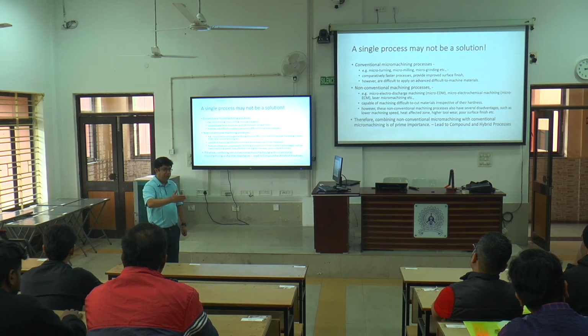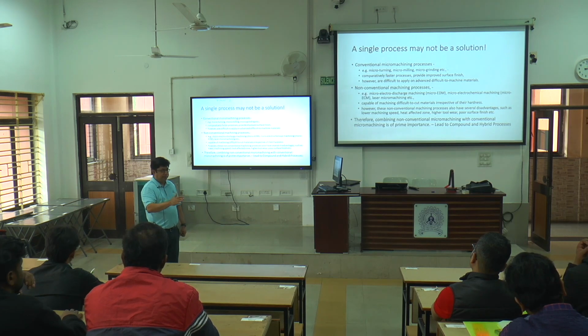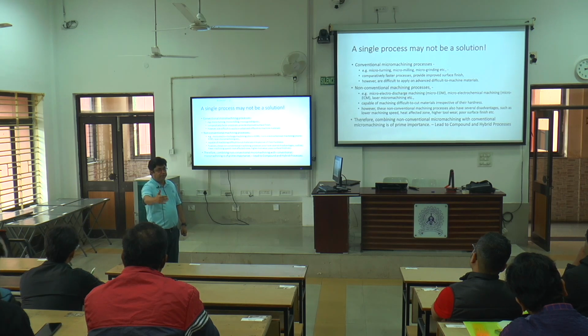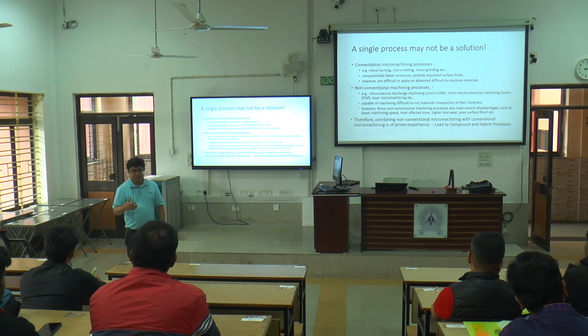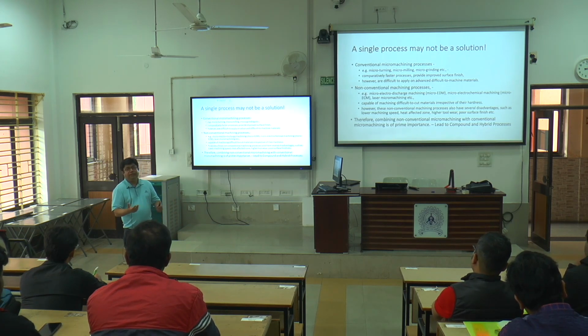So that means if you are machining, on the first layer there is some oxide formation, right? And then you have some recast layer, right? After the recast layer, you have some heat affected zone, and then you have the material. In the recast layer, definitely the properties are far different from the base material, and in the heat affected zone also, microstructure and phase transformation happen, so things change, right? So how can you actually get rid of those, okay?